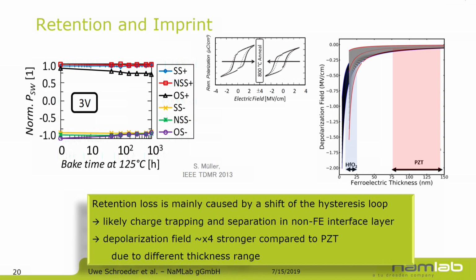And if you look at the comparison here for the depolarization field for the PZT versus the hafnium oxide case, the behavior is very similar for both. It's just that they both run in different thickness ranges. I mean, the PZT is typically in this 70 to above 100 nanometer range, and the hafnium oxide in this 10 nanometer range. And here, the depolarization field is about a factor of 4 higher compared to the PZT case. You would expect also a stronger injection of charges. And Alexei Gruverman's group will show tomorrow in the afternoon some more work on this imprint behavior.